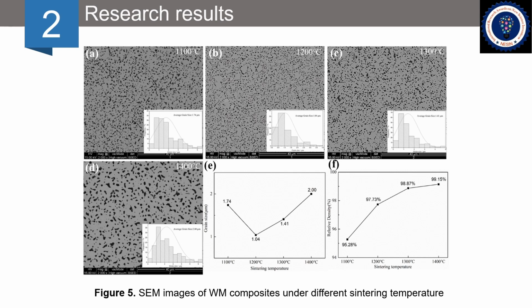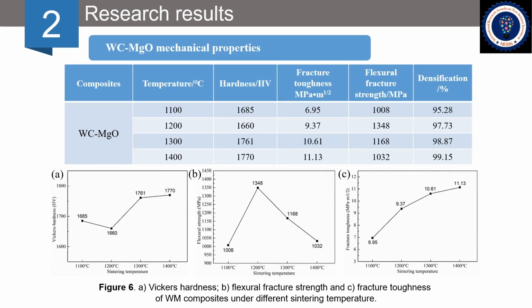Compared with traditional sintering methods, the SPS process promotes sintering of powder particles through electric discharge and spark plasma. Meanwhile, the applied extra pressure helps strengthen consolidation while limiting grain growth. Figure 6 displays the hardness, fracture strength, and the fracture toughness of the WM composites at different sintering temperatures.